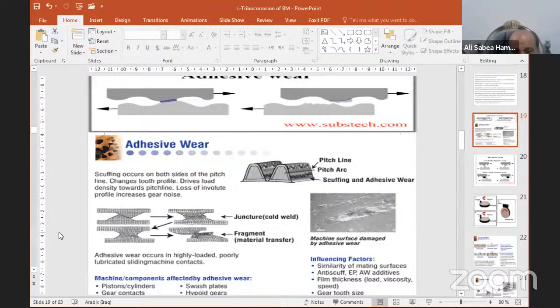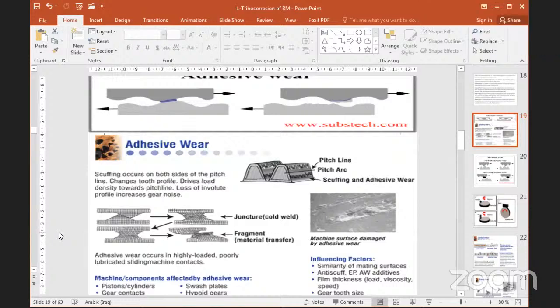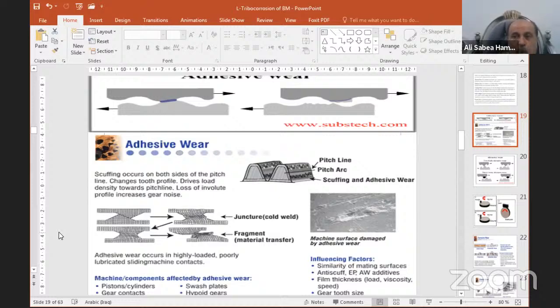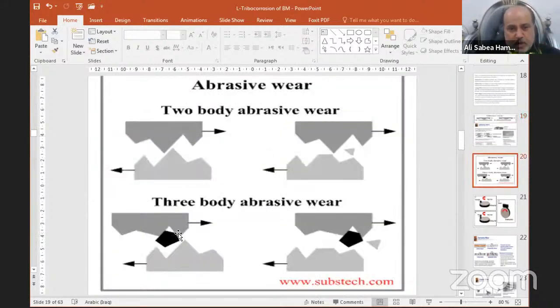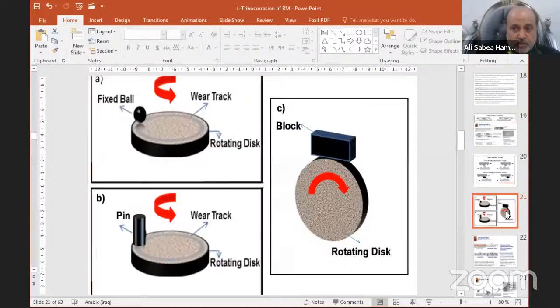Influencing factors: similarity of mating surfaces, and additives for lubrication, film thickness, load, viscosity, speed. Gear tooth size in a gearbox is very important in adhesive wear. In abrasive wear, there are two-body abrasive wear and three-body abrasive wear. The pin on disc method determines the wear rate: fixed ball, wear track, rotating disc. Another design for the pin on disc method.